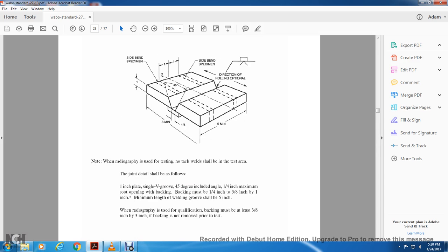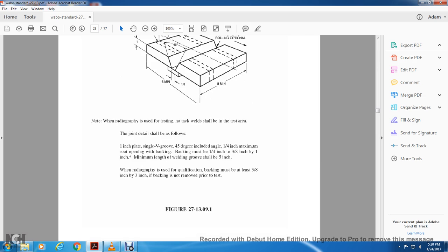The joint details should be as follows: 1 inch plate with a single V groove, 45 degree included angle, 1/4 inch maximum root opening. Backing must be 1/4 inch through 3/8 inch by 1 inch minimum. The welding groove shall be 5 inches. For radiographic view of the qualification, backing must be at least 3/8 inch by 1 inch, and the backing is not removed prior to the test.